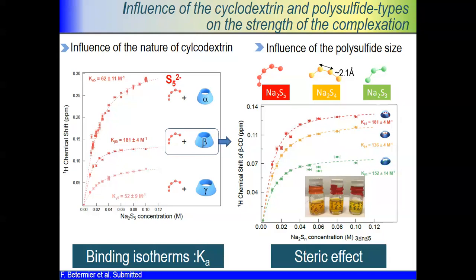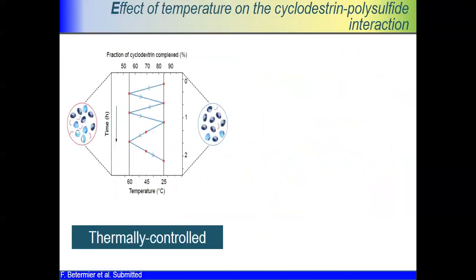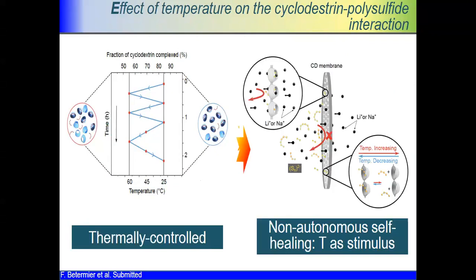So having this, we can go one step further. One thing that is great about cyclodextrin is that you can trap this kind of species, and what we found is that as a function of temperature, you can really release this type of species. So this clearly gives the first indication that, indeed, in this case, we can do non-autonomous self-healing using temperature as a stimulus. And you see very well how this will work.